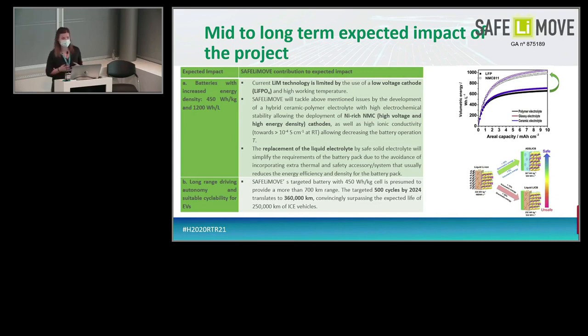So SAFELiMOVE aims to address, and is already addressing this, by the development of this hybrid electrolyte that will not only provide high voltage stability, that will allow us to move from LFP to NMC, and as we can see here, this will have a direct impact on the total energy density that we may reach, but also the increase of the ionic conductivity will allow us to decrease the operational temperature of these batteries below the current temperature that we may find in the market.